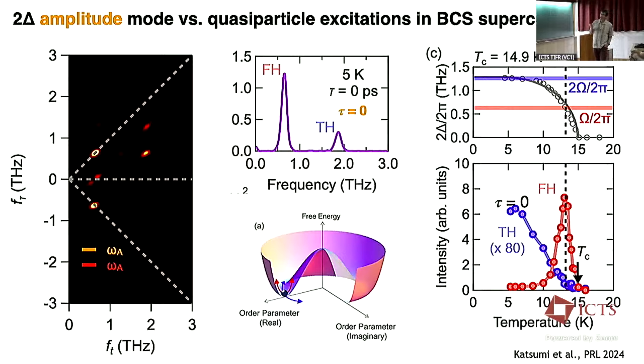One of the advantages of the 2D technique, 2D again referring to 2 frequency directions, 2 frequency dimensions, is that these different processes appear at different places in this 2-dimensional map. The 2-dimensional map is really a 2-dimensional spectrum. And these different places in this 2D map go by different names. So this particular one here, where we're using 2 pulses, but it's a chi-3 response, so I need 3 electric fields to feature in it. And so I either use 1 electric field from the first pulse, and 2 from the second, or 2 from the first and 1 from the second. And so this particular response here, which appears at that point, turns out to be very important for a lot of the experiments we do.